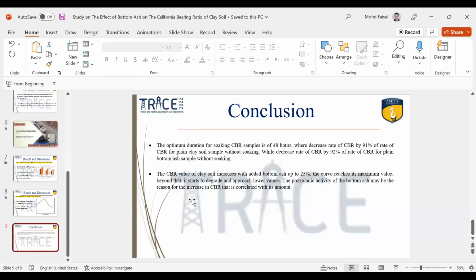Yeah, Faisal. Yes, sir. So tell me one thing. What about the bottom ash? How are you mixing the bottom ash in the soil? Yes, sir. We mixed the bottom ash with the clay soil manually by hand, and we added the optimum moisture content, OMC, of 8% after doing the compaction test. So you have worked out OMC for every composition? Yeah, for every composition. So you are able to achieve the required density as per the OMC?